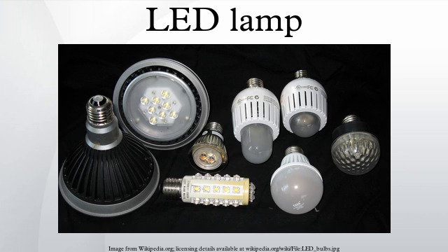Efficiency droop: the term efficiency droop refers to the decrease in luminous efficacy of LEDs as the electrical current increases above tens of milliamps. Instead of increasing current levels, luminance is usually increased by combining multiple LEDs in one bulb. Solving the problem of efficiency droop would mean that household LED light bulbs would need fewer LEDs, which would significantly reduce costs. In addition to being less efficient, operating LEDs at higher electrical currents creates higher heat levels which compromise the lifetime of the LED.